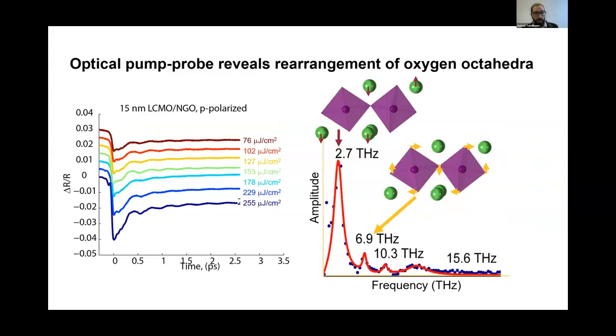So if we do conventional pump probe spectroscopy, then we can see, at least below the switching threshold, what the material is doing to respond to this photoexcitation. And here are some pump probe traces taken as a function of fluence at 80 Kelvin on an LCMO NGO film. And these are all below the photo switching threshold for this film. So this can all be done stroboscopically. And what you see is some very strong coherent oscillations here. These are this 2.7 terahertz mode, and some smaller oscillations, which you can make out just at the beginning here.